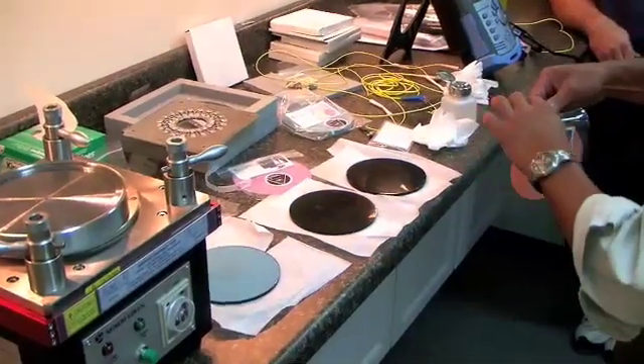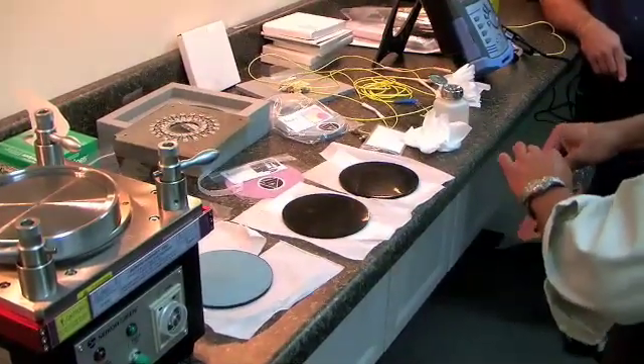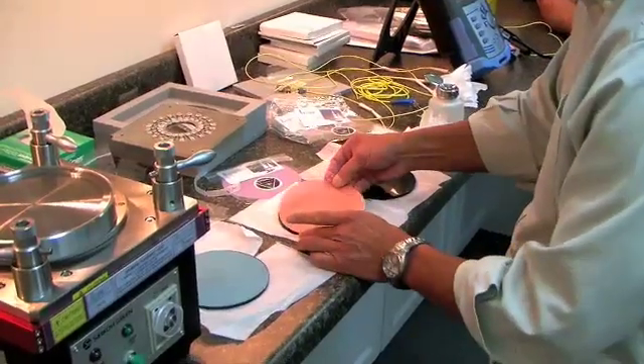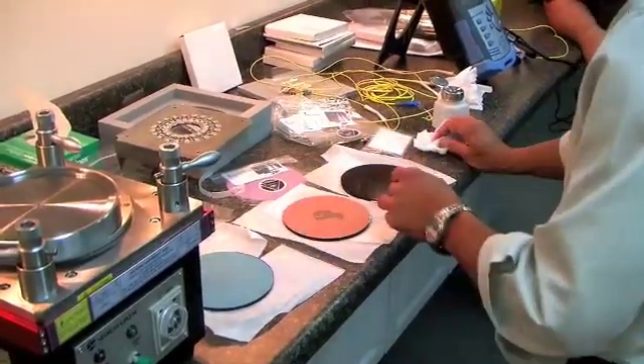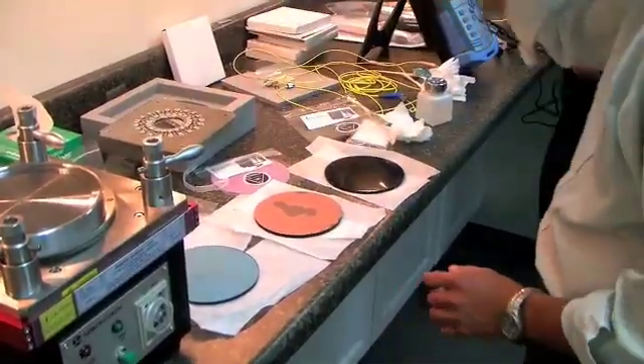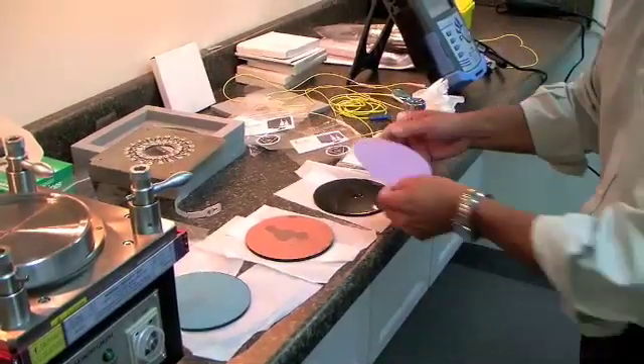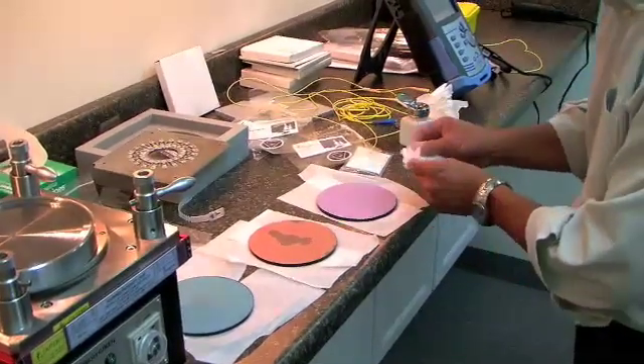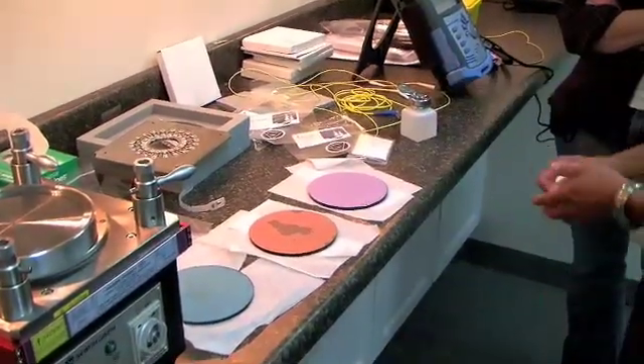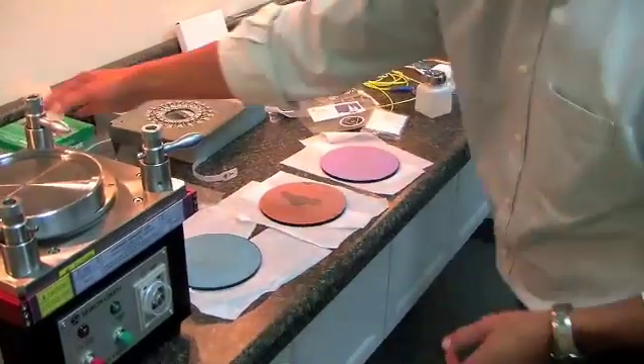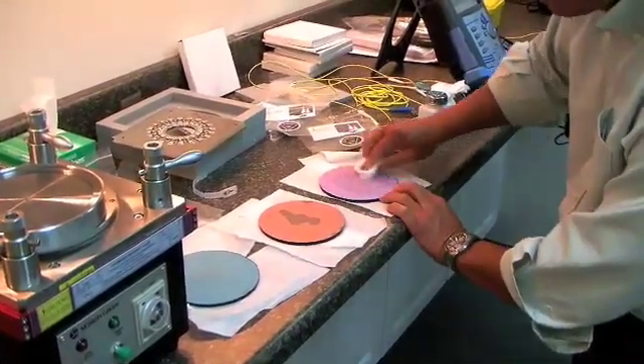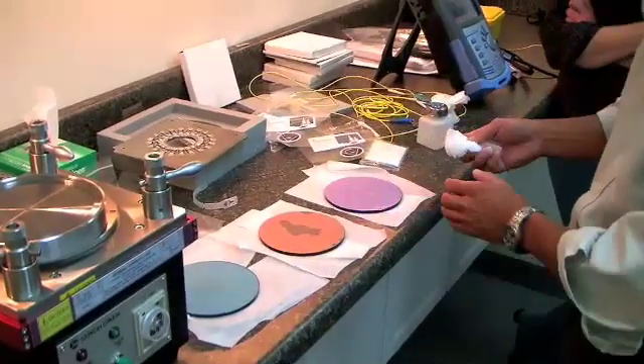The second step would be a 5 micron diamond. And they are color-coded so that you can always keep track of what it is. This will last about 50 times. The blue ones do not last because they get clogged up. Here's one micron diamond. And I'm going to clean each film prior to use. What I'm doing now is just making sure that they stick. To clean films, you basically take kim wipes and alcohol and start from the middle and work your way out to remove fingerprints and any particles.